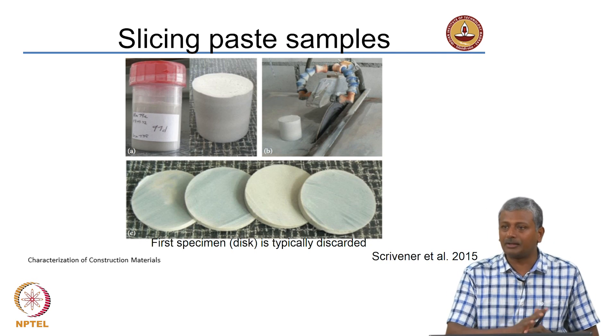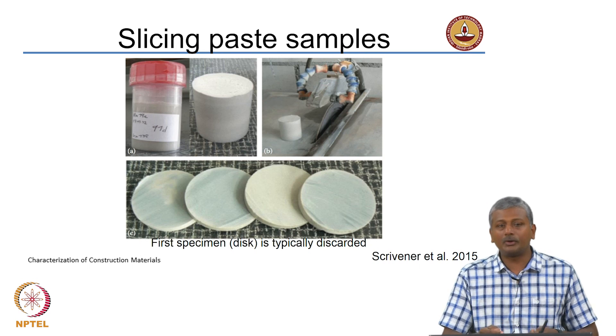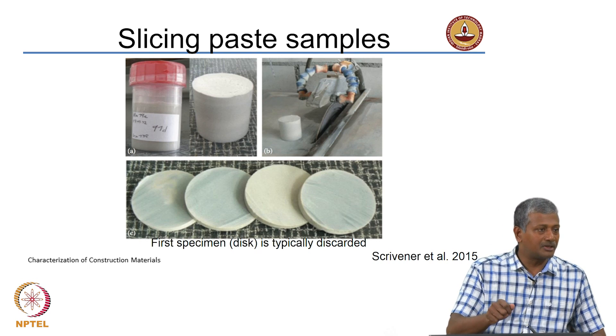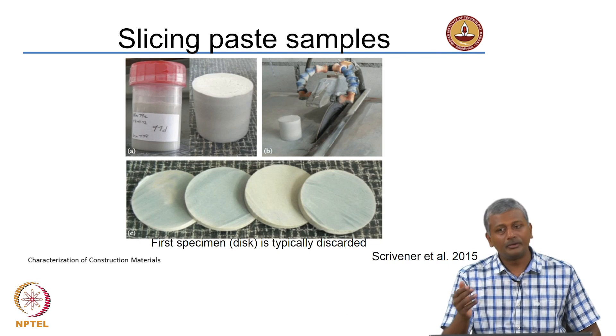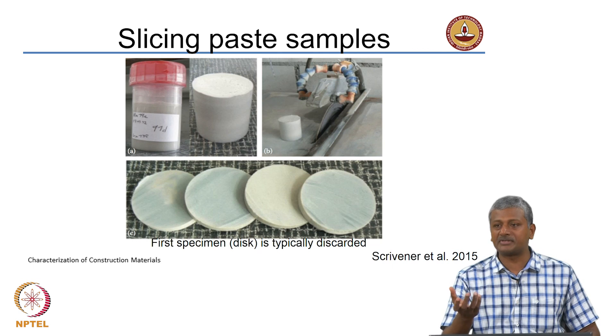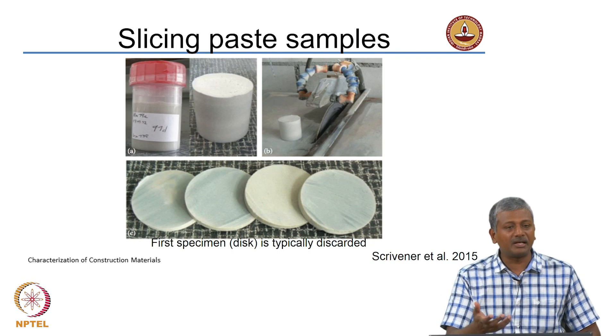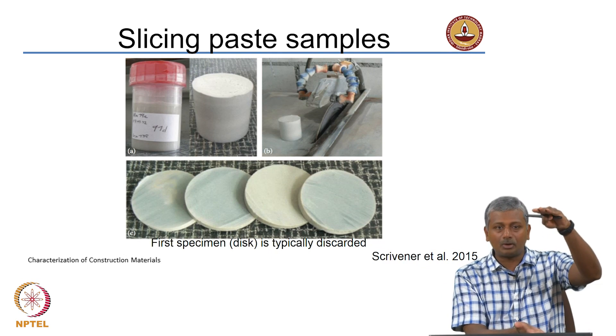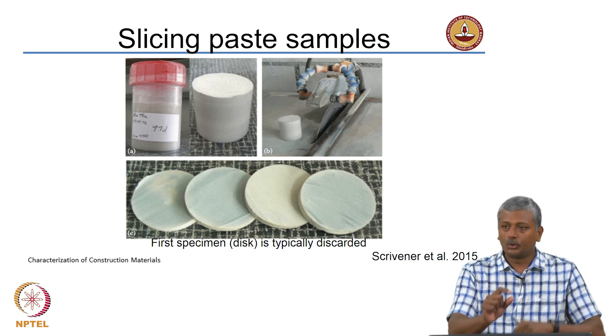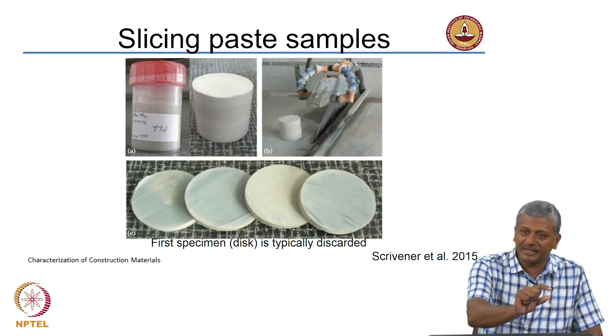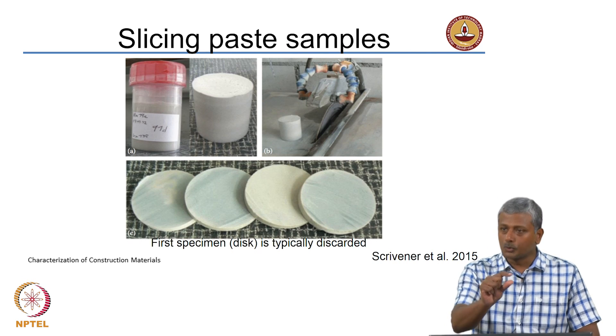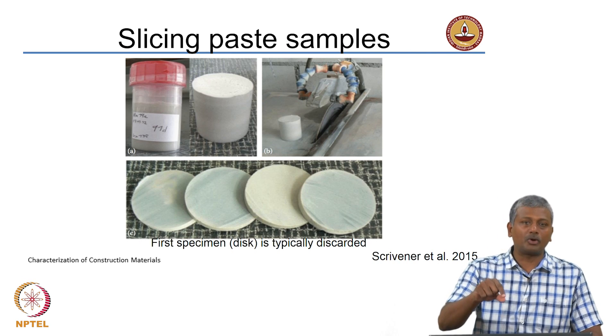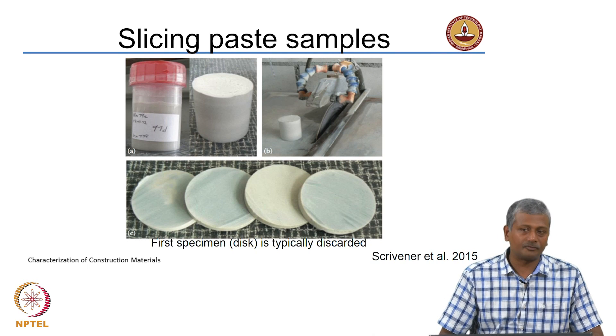The only thing is you need to embed this in epoxy and then do the grinding. You do not need to break off chunks of the material. When dealing with concrete or mortar, you can either slice it or, better still for a most representative sample, what is typically done is when you crush the concrete cubes for compression, you take a small chunk of mortar from inside that concrete and then impregnate it in epoxy to prepare your specimen.